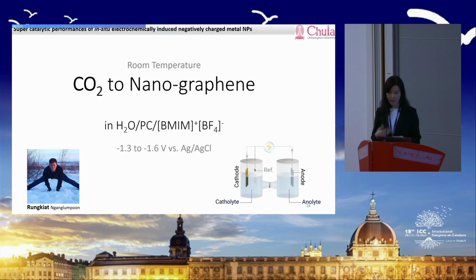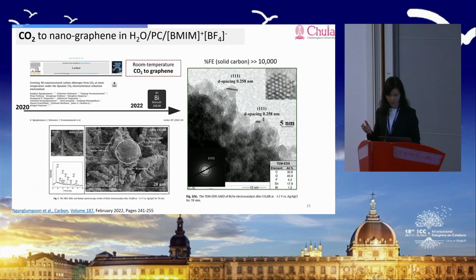And in our case, this is one of our first studies, way back in about 2020, where we performed carbon dioxide reduction reaction in an electrochemical system. But it turned out that we produced a lot of graphene carbon as a product. This is bismuth particles deposited on tin foil. And yeah, the first question: maybe it's just some carbon from your electrolytes? No, we have checked, there's no change in the form of our electrolyte. We have a little bit of CO gaseous products, but the major product here is nanographene, if we look at the structure.